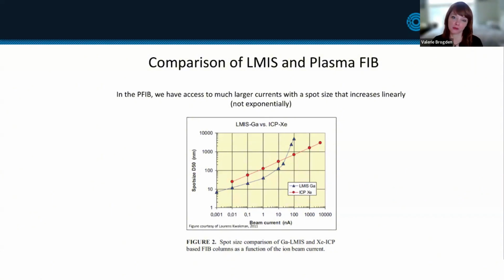So it'll have a slower removal rate, but it'll be a little bit cleaner of a substrate. And then I'll add this one last point. If you happen to be cutting through an organic substrate containing carbon, you can use an oxygen beam, and that works great for removing artifacts in organic substrates and biological substrates, because what happens is the oxygen combines with the carbon in your substrate. And so you have a chemical removal mechanism in addition to just the mechanical sputtering of the beam. And that results in a really clean, nice looking cut face on organic substrates. So that's my advice for your question.